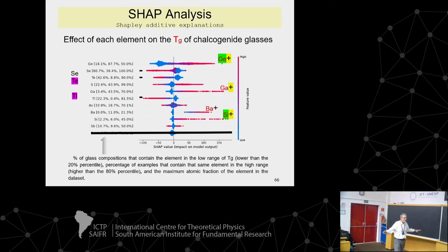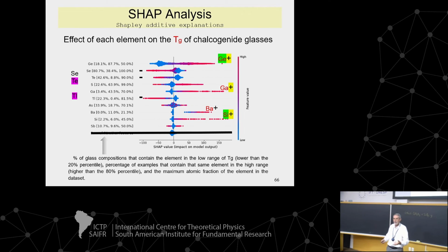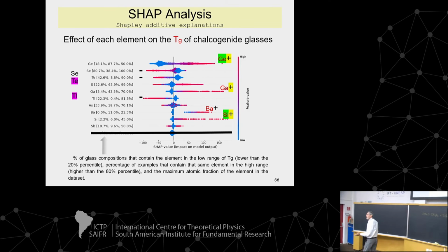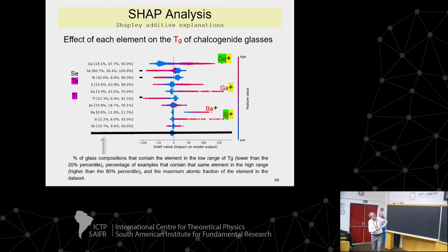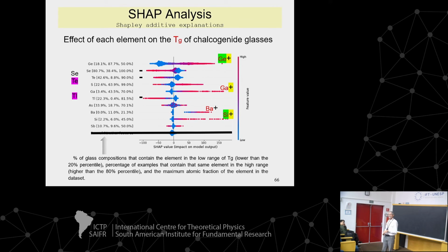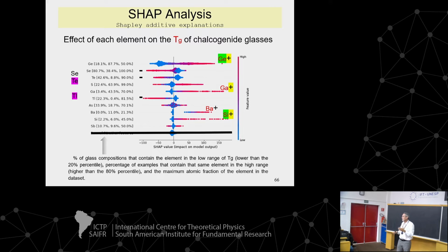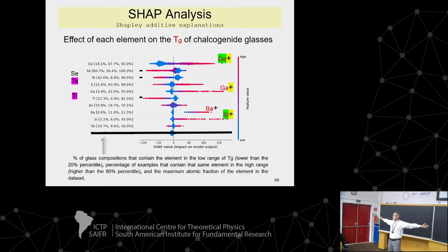So even if you don't know anything about machine learning, you don't care about machine learning, you're a glass guy trying to develop a new glass, you work for an industry, you now focus on germanium, gallium, barium, or silicon, rather than the whole periodic table. Or if you want a glass with low TG, go for selenium, tellurium, or thallium. These are glasses with very low TG, so minus 100 degrees Celsius in relation to the average. So you see what I mean. Instead of looking at the whole periodic table, machine learning is teaching us, look here, not here. This will make the lives of glass designers, of researchers, much easier.